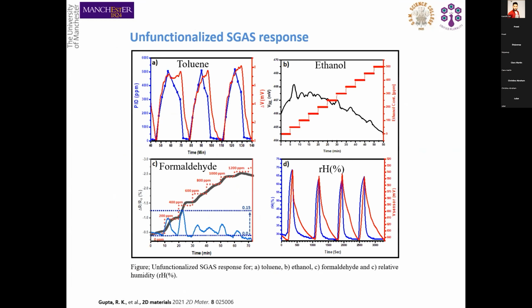Whereas we also did this when we do not have this suspended graphene structure functionalized, and they interact with the toluene properly, in a good way, as well as with the ethanol and with the relative humidity. So a sensor functionalized with the TFQ does not get affected by the toluene, ethanol, and relative humidity exposure, but a sensor without any TFQ interacts and provides a response. So that confirms the selectivity.